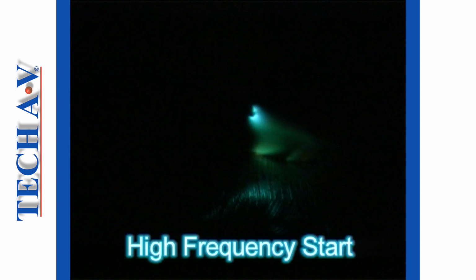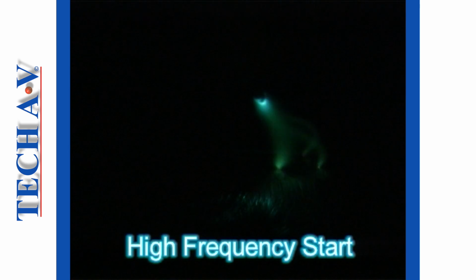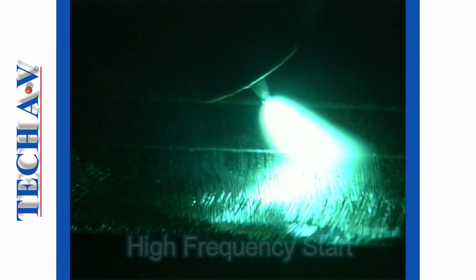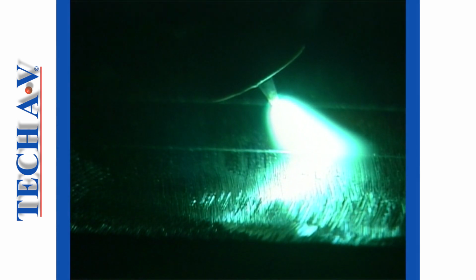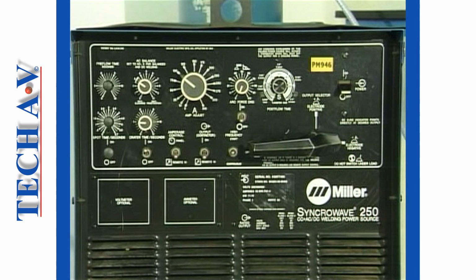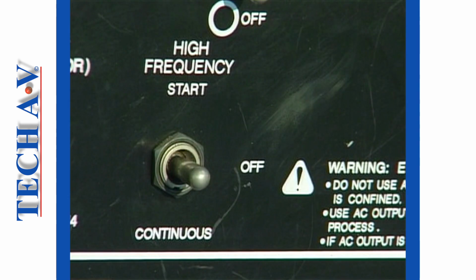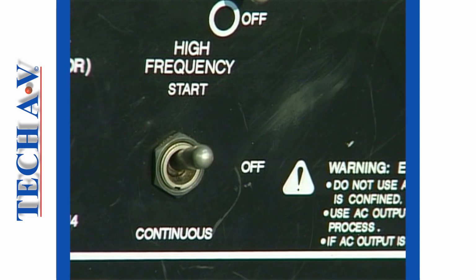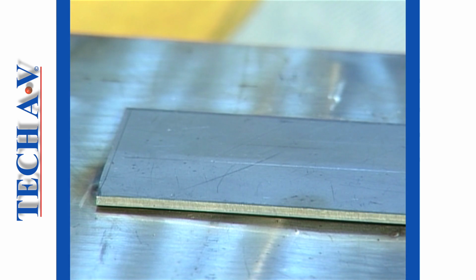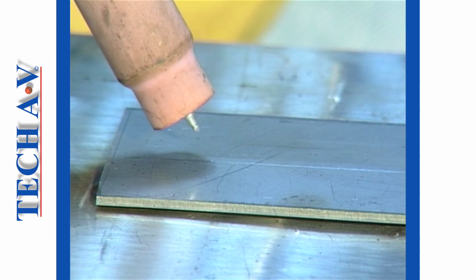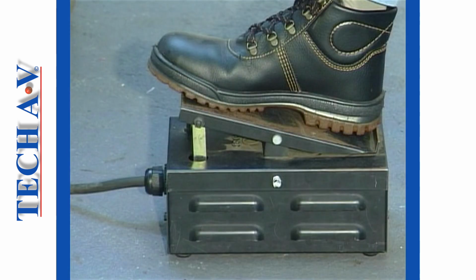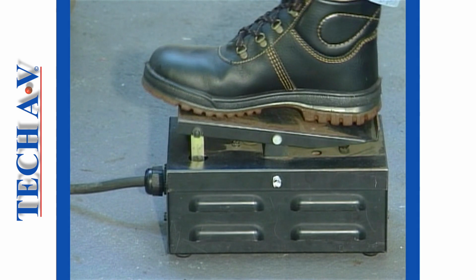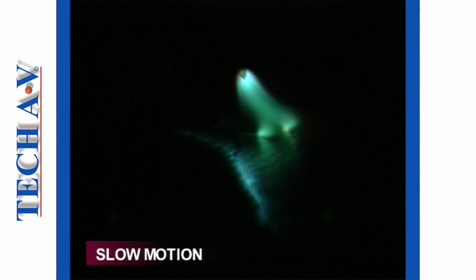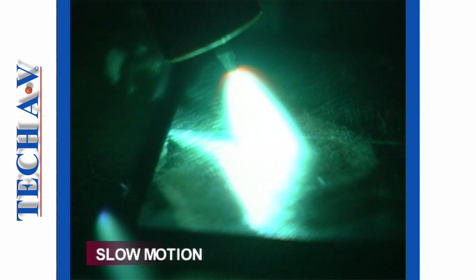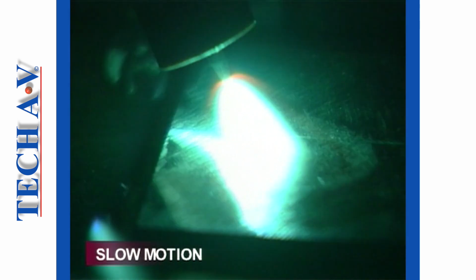The arc will strike as the electrode breaks contact with the metal. The next method, and probably the best DC strike method, is known as high-frequency start. This method allows the arc to strike without the electrode making physical contact with the metal. Most TIG power sources will include a high-frequency selector switch. Switch this selector, HF, to the on or to the start position. Now hold the electrode about 4 to 5 millimeters above the workpiece and then activate the foot pedal or the thumb switch, whichever applies. A high-frequency arc will jump across the gap. After about 1 or 2 seconds, the main welding current will flow and the HF will automatically cut out.